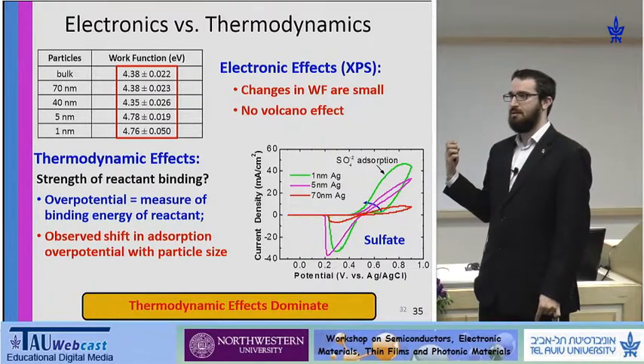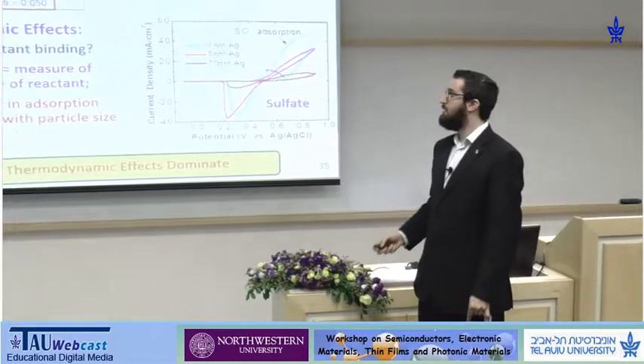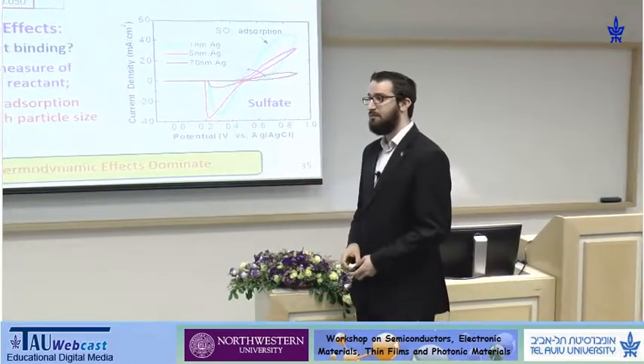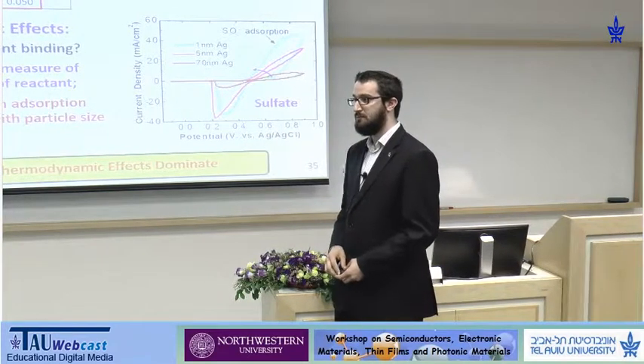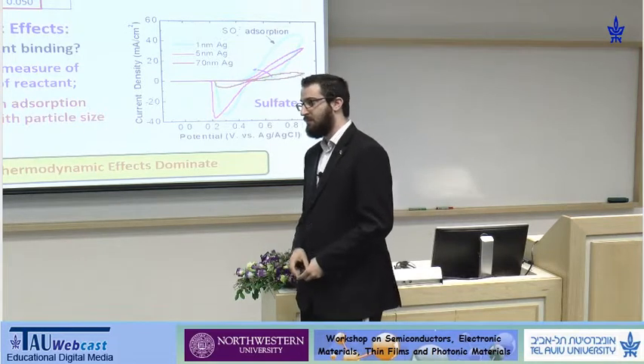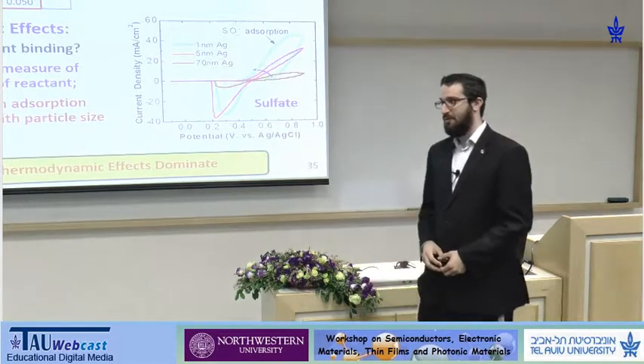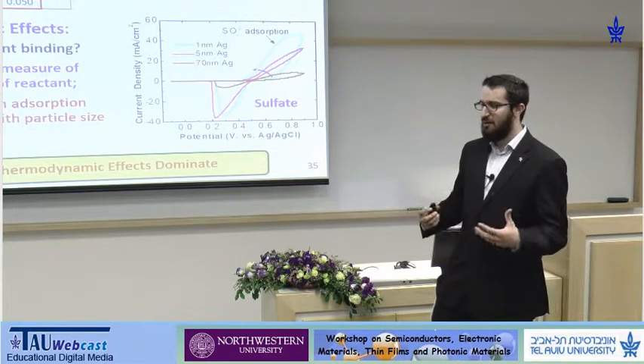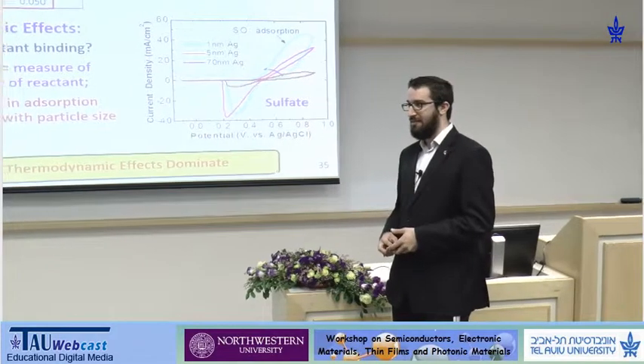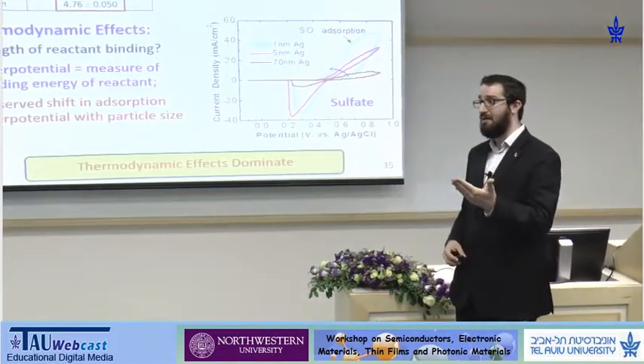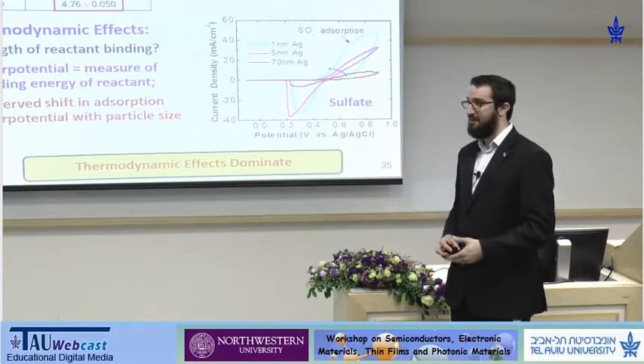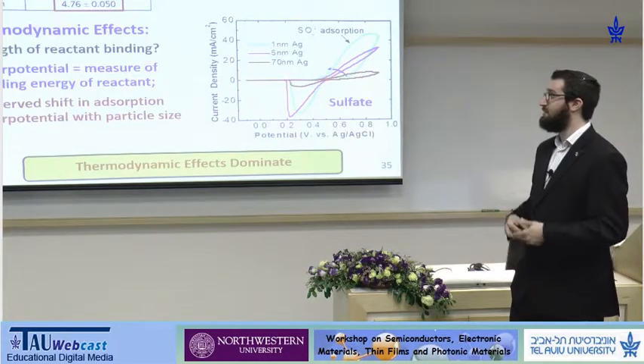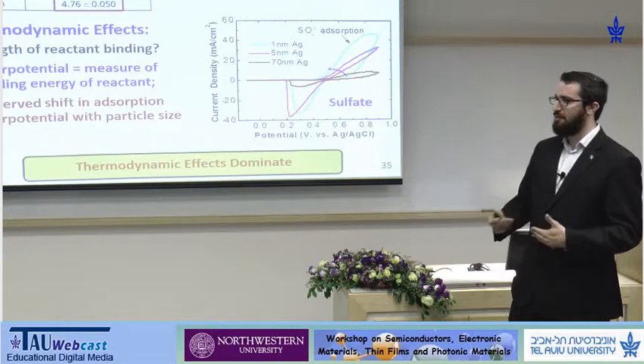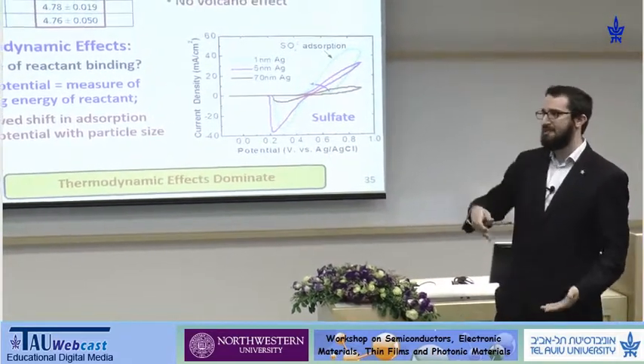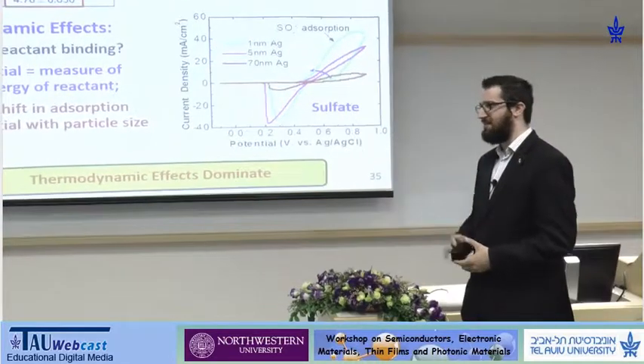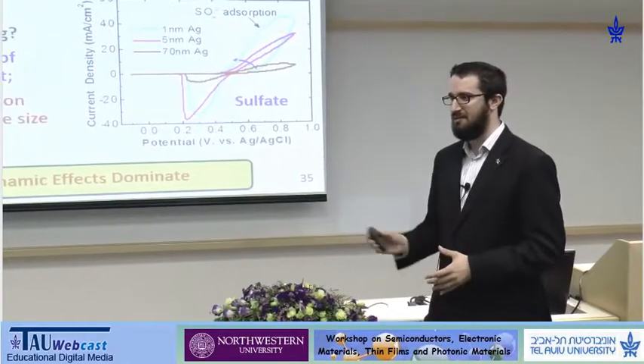More questions? Yes, please. I had a question about going towards the intelligent design of the catalyst. In terms of electronic structure engineering, usually I hear about the D-band model for catalysts. Are you trying to approach the electronic structure? So obviously this is a consideration we're looking at when we're talking about doping molecules. There's a lot in the literature about the position of the D-band and its effect on catalysis, since it's widely known that the D-electrons contribute a lot to catalysis. So the variation of the D-band that we would play with would largely come from changes in composition and the atoms that we choose to dope our surfaces with, and not so much changing the structural or the textural aspects of our surfaces.